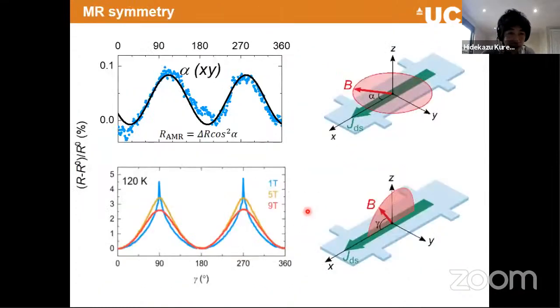Right, so that's exciting. And then also I just want to give a particular mention of this interesting magnetic resistance asymmetry or anisotropy. When we rotate the magnetic field in plane, so the moment is following this direction, we can see the magnetic resistance of about 0.1%, which is similar to the value that we normally get for the transition metal ferromagnet. However, when we rotate it out of plane, what we noticed was that the change of resistance is about 50 times bigger.